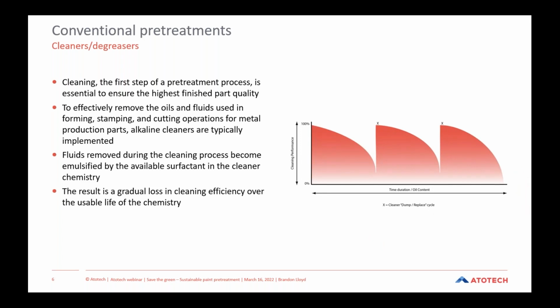And you can see that depicted in the diagram on the right, where we see the time duration or oil content along the x-axis and the cleaning performance along the y-axis. As you would expect, you would achieve 100% cleaning efficiency at a new cleaner makeup. And as time goes on, the cleaning efficiency will gradually decrease until there's a point which necessitates a new cleaner makeup. So without the proper process control, poor cleaning can have a really big impact and lead to diminished final part quality.